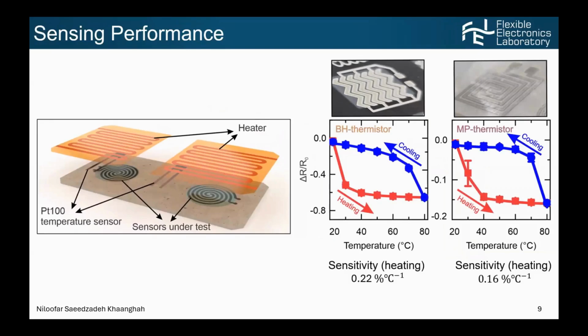Here you see the plot of normalized resistance versus temperature, which shows a significant hysteresis. As we start heating and cooling, there is a steep slope showing that the sensor is highly sensitive to the heating and cooling. However, as soon as the heat dissipates into the substrate, the sensitivity goes down. So by taking the linear behavior between 30 to 70 degrees, the sensitivity for the heating process is 0.22% per degree, and 0.16 for the mother of pearl. And this large hysteresis is comparable to other thick and voluminous substrates, and is normally attributed to the heat capacitance of the substrate that retains and releases heat gradually.